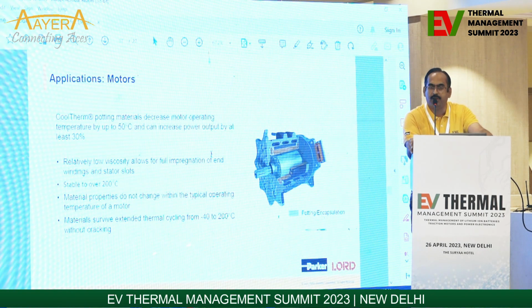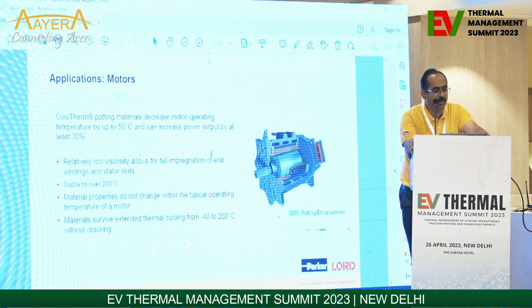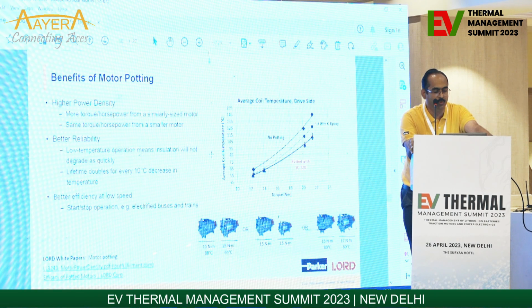So this is application in induction motors, where you can get a delta T of nearly a 50-degree drop in the temperature by using our potting material, and your power output can also be increased by almost 30%. These are potting materials which are stable up to 200 degrees centigrade. The best example I can show you is where we have studied these motors with different materials.